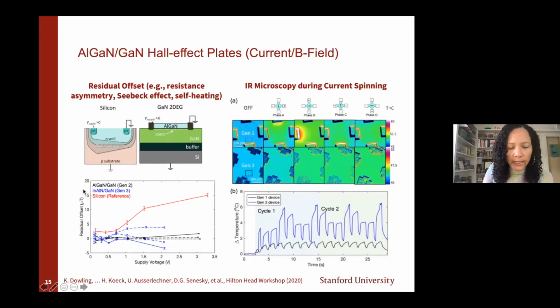And what we found through Karen Dowling's work is that silicon devices have, again, this doped well, and there's actually thermal gradients due to this implanted well, right? It's not a confined portion in which you're creating this bias. And silicon actually has quite a significant Seebeck effect. So if you have thermal gradients across your device, you will have some voltage that's generated, and that is a major contribution to the offset, but also self-heating and resistance asymmetry as well.